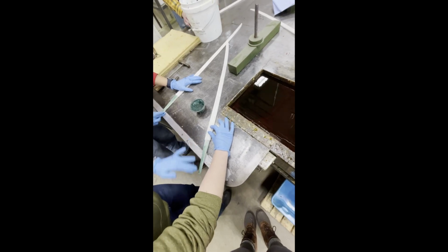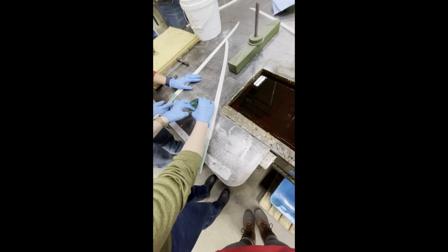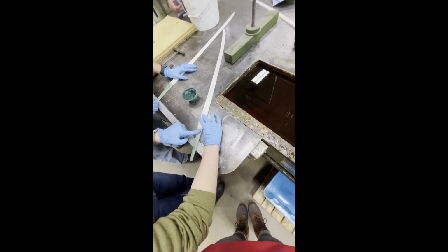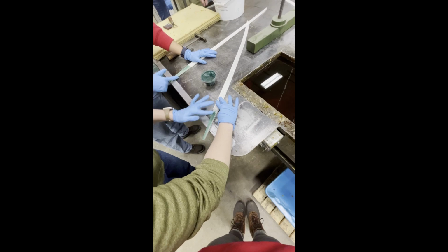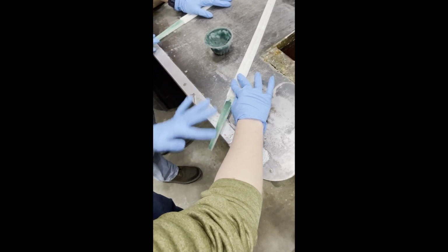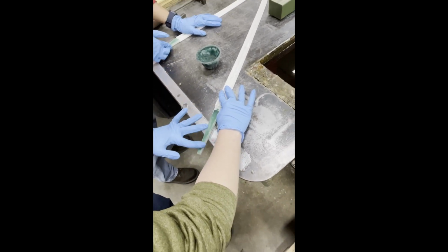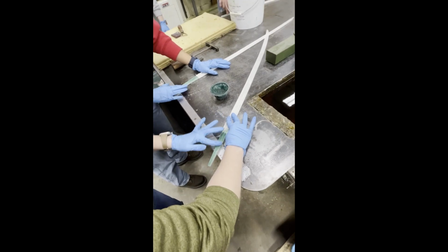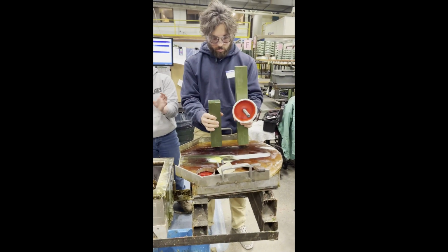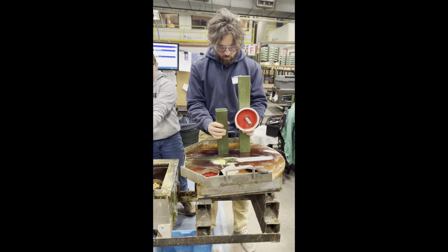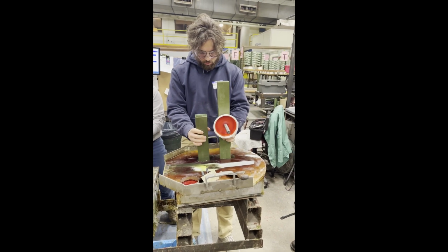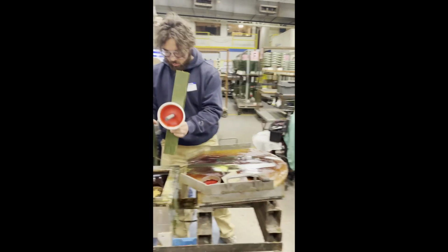And so we chose to use the investment casting process to cast this sword. This is because investment casting has excellent dimensional stability and surface finish, which allowed us to cast this long, thin sword very close to its final dimensions, cutting down on the amount of post-processing that we would have to do.